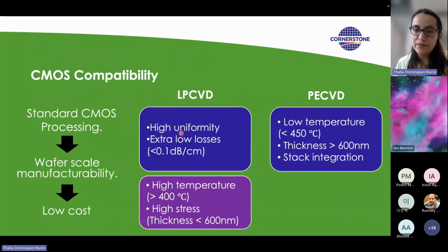Now, if we go back to PECVD, on the contrary, what we see is that in the PECVD layers, we have a very low temperature. What we say is a low temperature for CMOS fabrication processing is less than 450 degrees. The other thing is that the technique itself allows us to deposit thicknesses greater than 600 nanometers. We fabricated waveguides up to 1 micron or 3 microns of silicon nitride, which means that because it's done at a low temperature and you can achieve very thick layers, you have more flexibility in terms of the stack integration. So you can put it on top of other materials, you can integrate it with other materials on top, or you can integrate other materials on top of it as well.